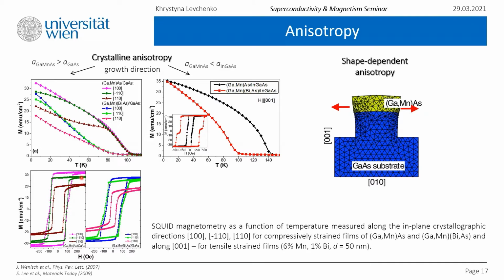Then there is again, as mentioned, -110, which is unequal to 110, which is the hardest axis for our material. The addition of 1% of bismuth did not change the situation with anisotropy. Actually, these measurements were performed on the same set of samples that proved themselves of high quality during the crystallographic structural check. And in the case of the indium gallium arsenide buffer, we see that there is already some skew introduced